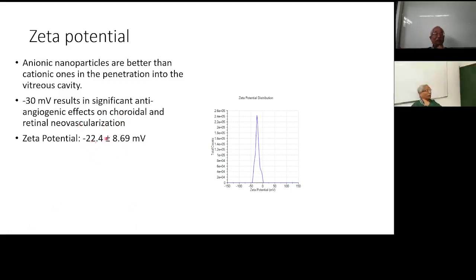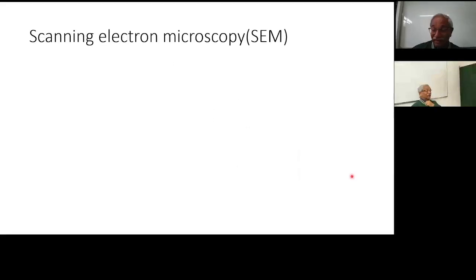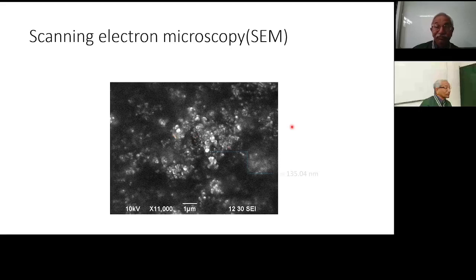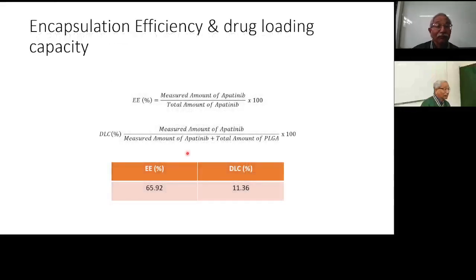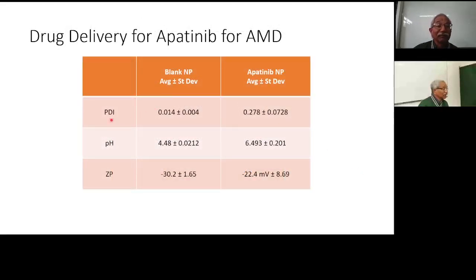So our zeta potential was minus 22.4, while they were expecting minus 30 would give you better results. This is our zeta potential distribution of the nanoparticles with apatinib. Scanning electron microscopy of the apatinib looked like this. Our mean particle size was around 135 nanometers, and there were even smaller particles, so this was good. Our encapsulation efficiency for the apatinib was 65.9%, and drug loading capacity was around 11.36%. And the polydispersity index, PDI, was 0.04, which was very good.